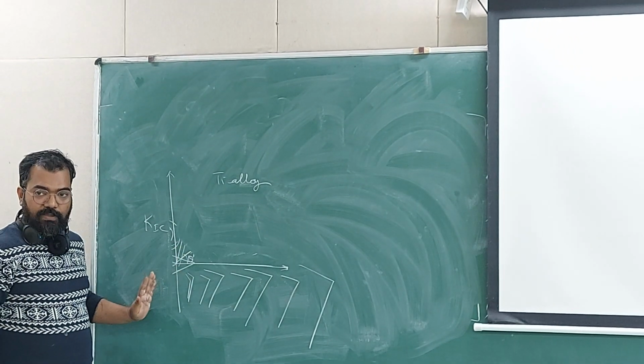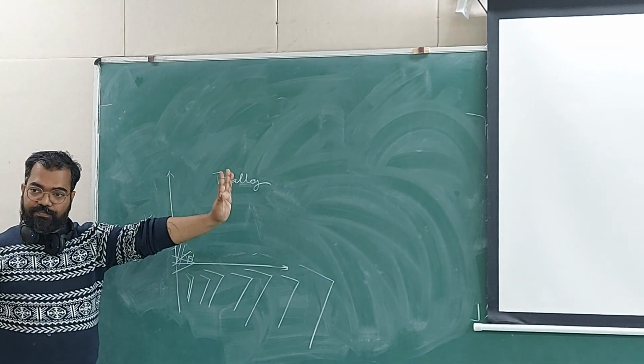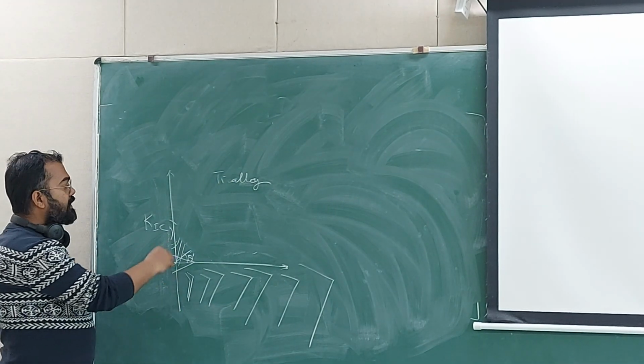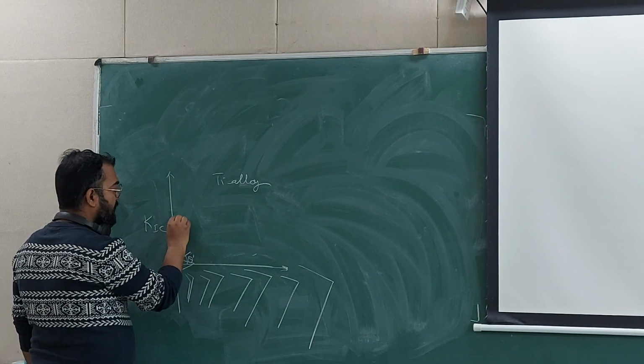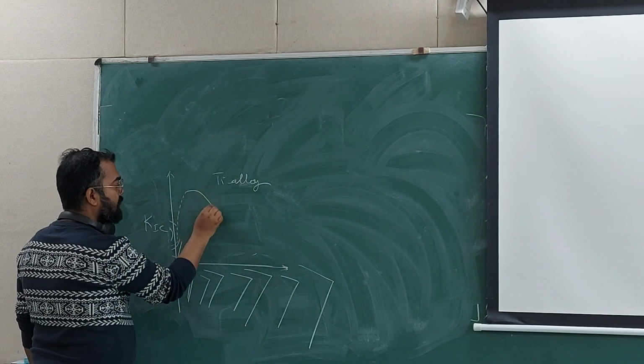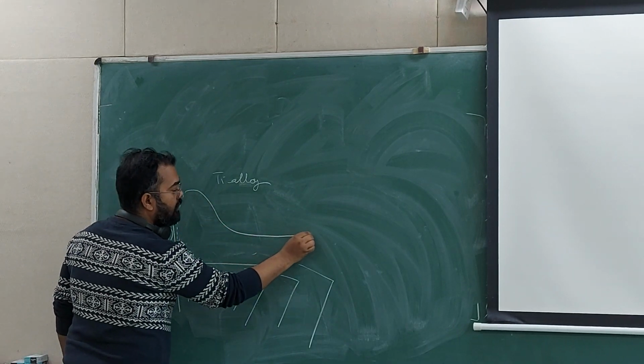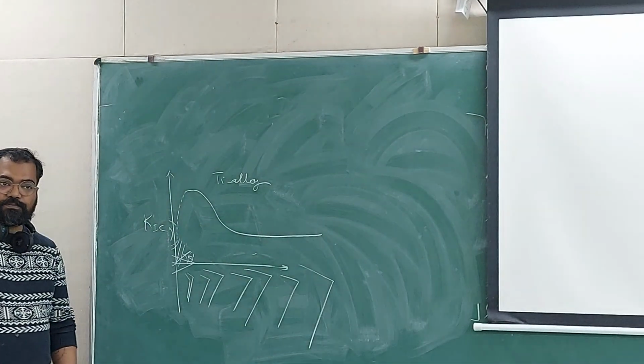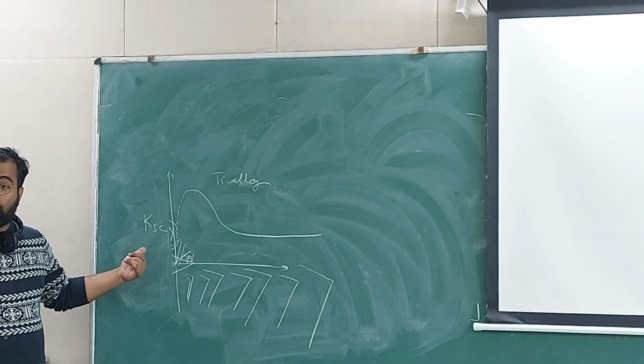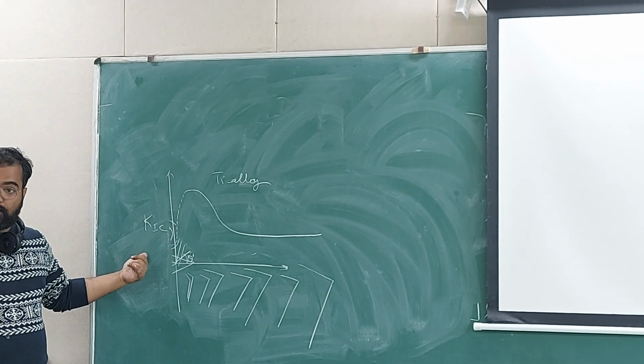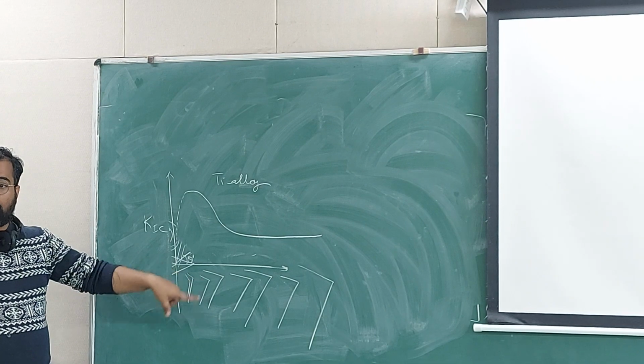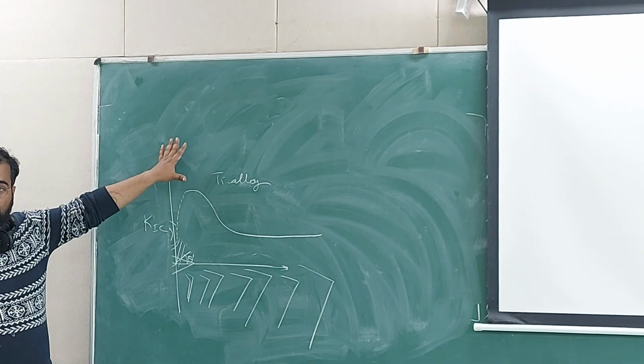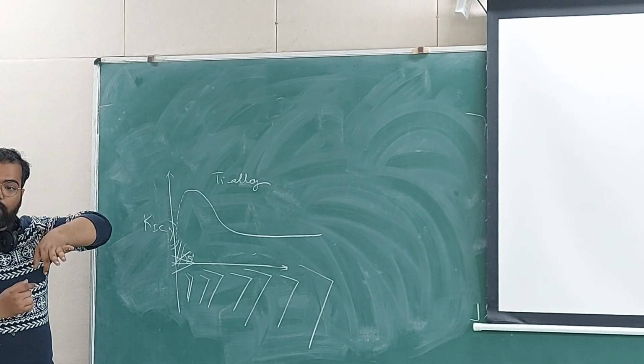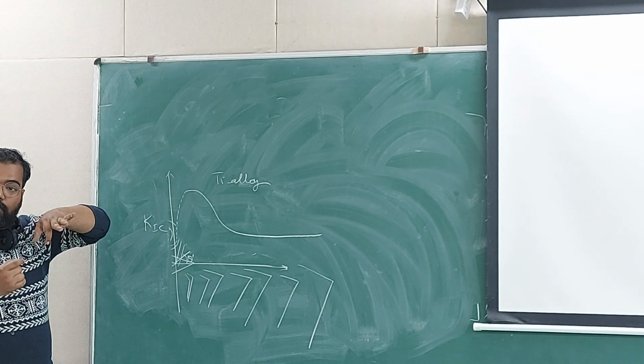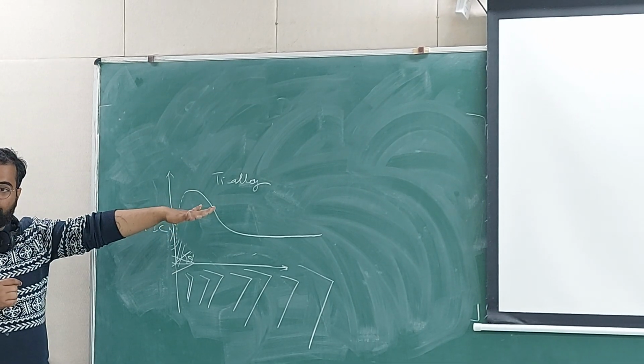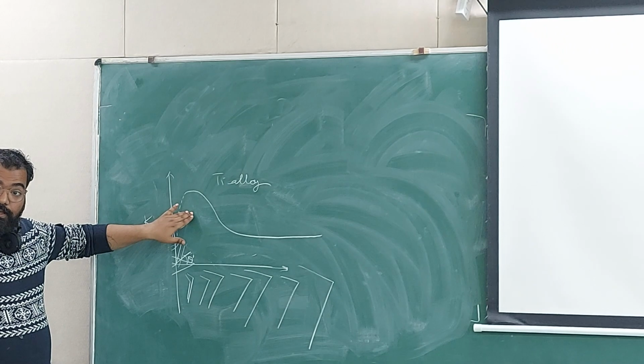So what am I changing? Plane stress to plane strain. If I plot it, the initial region is unknown, and then it shows this kind of profile. It is not K, it is K1c. For different thickness values, you have done the fracture toughness testing and found the critical K value for which the crack starts propagating. That value you are plotting.